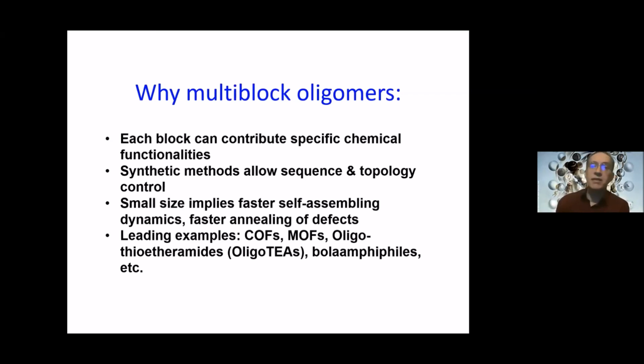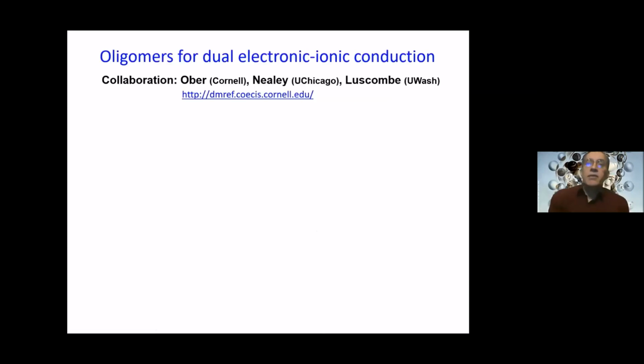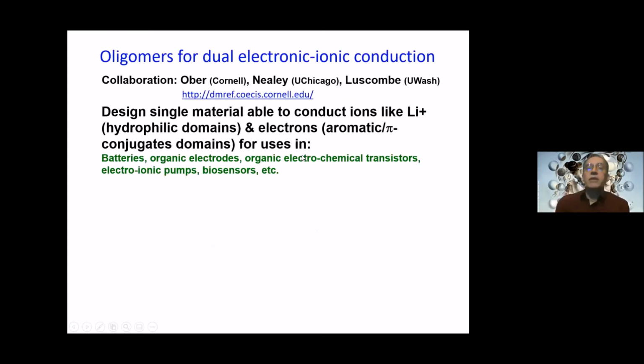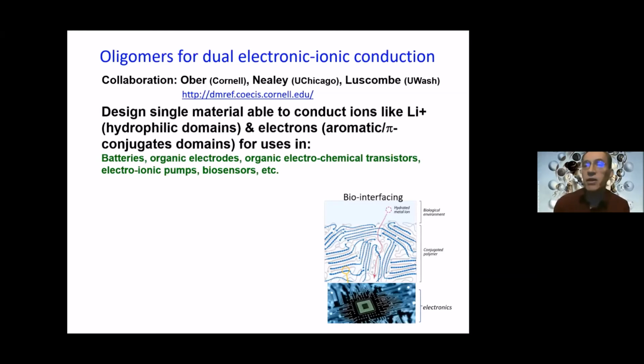And there are many interesting materials out there that people explore, but for this talk, I will just be concentrating on these block oligomers. So I'm part of a team that has 3 other groups that do experiments, synthesis, characterization. You can read about us in this webpage. But our goal is to design a single soft material that will be able to conduct both ions, like lithium, say, through hydrophilic domains, and electrons through, say, pi conjugated domains, so that this can be used for batteries or biosensors and so on. In fact, that corresponds to the holy grail in biointerfacing, because if you think about it, in the biological realm, signaling happens through conduction of ions, while in the electronic domain, it happens through the conduction of electrons. So having a material that can do both will be extremely useful.